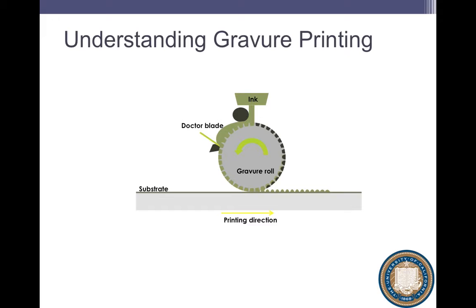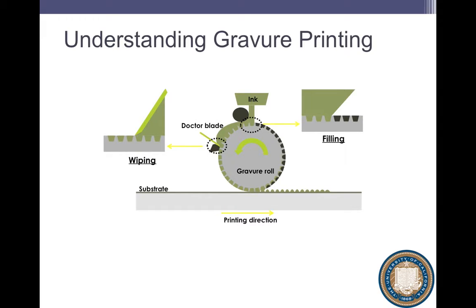So first, let me explain briefly what gravure printing is. In gravure printing, you have a hard metal cylinder, typically stainless steel coated with chrome or copper coated with chrome, and you ink it with an ink. Now the ink has to go in and fill the cells that are etched into the cylinder. So the first process that matters then is filling. Once the ink has filled the cells, it's everywhere. So you have to wipe the excess ink off, and that is done using a doctor blade that scrapes the ink from the regions you don't want it and ideally leaves the cells completely filled, and we call that wiping.